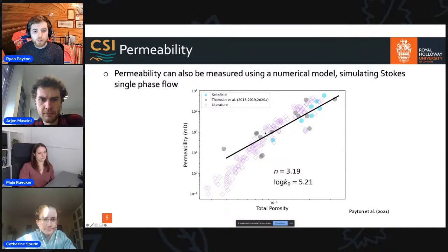But as we hit that 10% mark again, the literature data starts to show a kink and starts on a different trajectory. So we're hoping that once I've managed to complete the permeability simulations, we'll get more data points around here and see where that kink starts to form in our data, and again, better constrain that permeability, that percolation threshold.